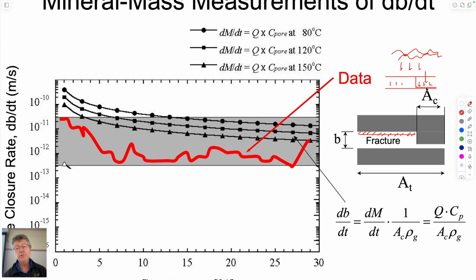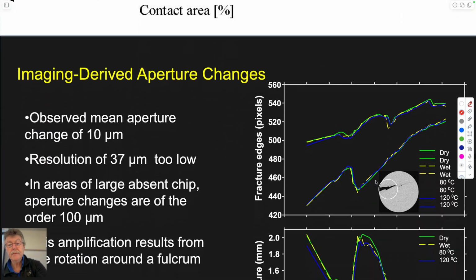And if you apply a stress to a mineral, then that mineral will dissolve more rapidly than if it's unstressed. So pressure solution is exactly that. It's the propensity for a mineral to dissolve under stress, preferentially faster than it would do on a free face. So the mere fact that we're net dissolving materials and the aperture is going down suggests that the material is coming from this contact by pressure solution, and that's the mechanism that's going on.